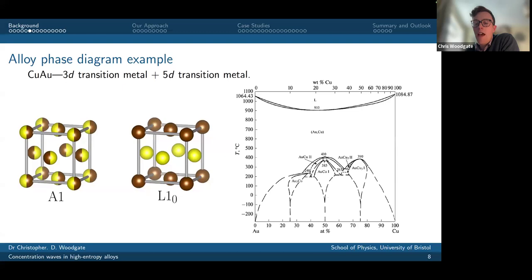What's happening there is that it's no longer favorable for the atoms to form this disordered FCC phase. Instead, the thermodynamically favored phase is this L10 phase, where the copper and the gold atoms are forming layers. So there's still an underlying FCC lattice, but there are alternate layers of copper and then gold, and then copper and then gold, and so on.